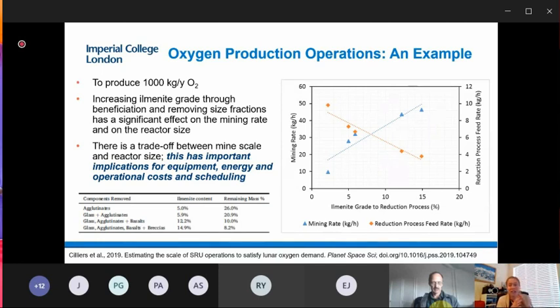Now, I should say this is entirely theoretical, and it's just an assumption-based thing. Actually, we may wish to target the glasses. There's an argument that the glasses would be a better source of oxygen, or would produce oxygen at a lower temperature. But if we're just looking for now at what this would do to our process, we can see on the graph on this slide, on the x-axis there, we've got the ilmenite grade. So as we keep stripping out more fractions, the ilmenite grade increases.